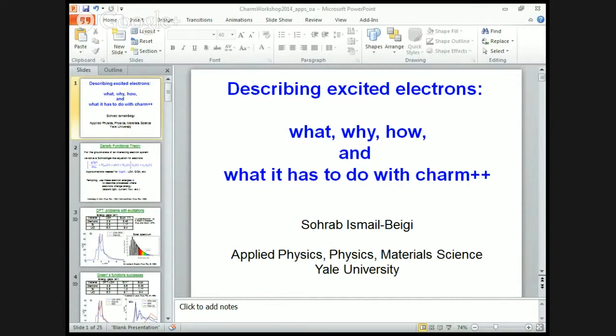So that's why it matters to get these numbers quantitatively. The typical quantitative accuracy you need is about 0.1 electron volts to be believable for an experimentalist to bother talking to you, to spend the effort to fabricate the material. And this theory is too poor. The reason it's poor is because it's a ground state theory. Its job is to describe the ground state of electrons, not when you're excited.